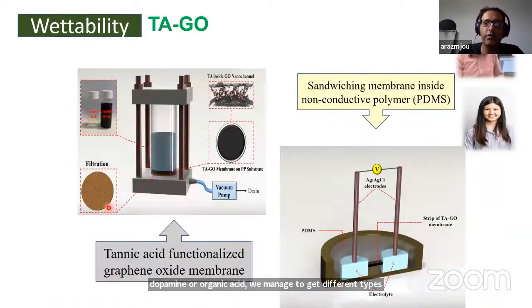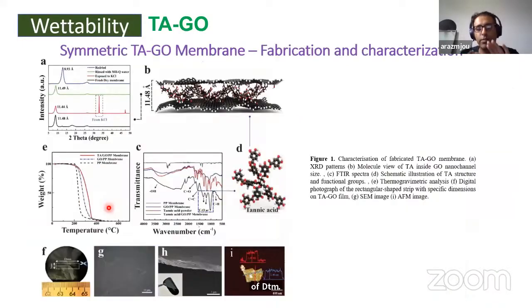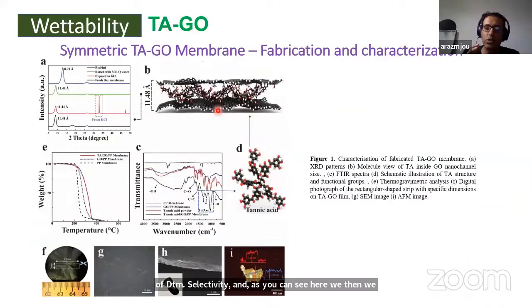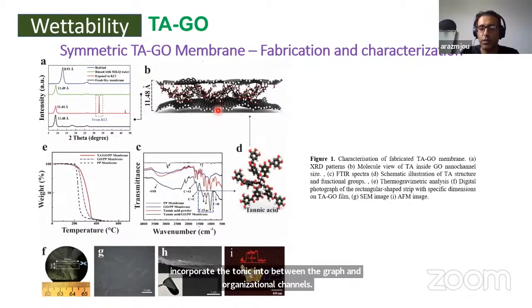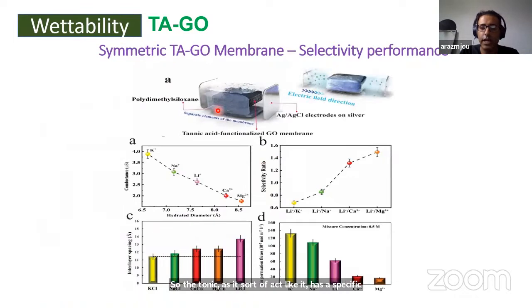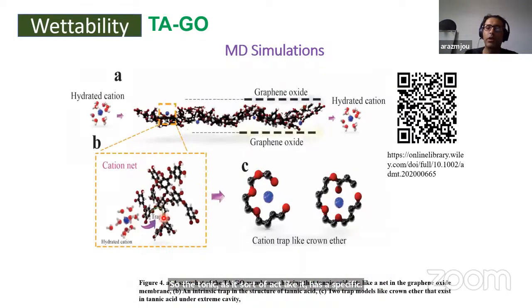As you can see here, when we incorporate the tannic acid between the graphene oxide nanochannels, the tannic acid acts like a specific cation trap, like crown ether. This crown ether has a very interesting molecular structure, because it only allows a specific ion to sit in the center of the molecule. In this particular case, we found that the tannic acid has a natural crown ether-like molecular structure which holds lithium and allows other cations to move through. That provides lithium selective membranes.